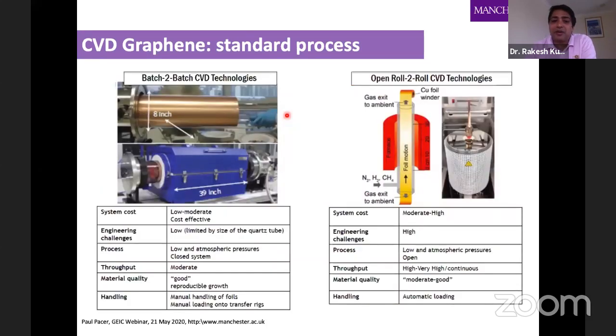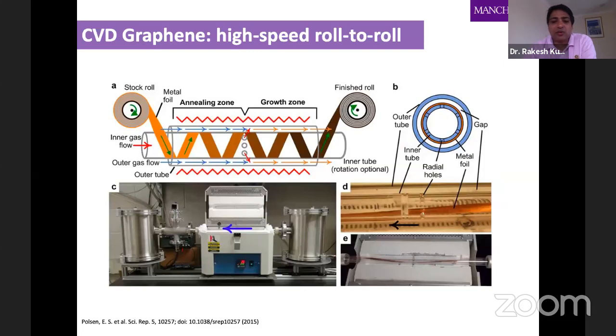The other method where we can generate large scale CVD graphene is called batch-to-batch or roll-to-roll CVD technology. Again, I would say these technologies are in their early stage in terms of quality, in terms of quality control, and in terms of properties. We're still working on it in order to get a high quality graphene for electronic devices. So there's a roll-to-roll method. They still use the same technology of heating the materials, the copper wire or copper film, in a CVD furnace, and then breaking the source of carbon from acetylene or methane in order to nucleate on copper film.